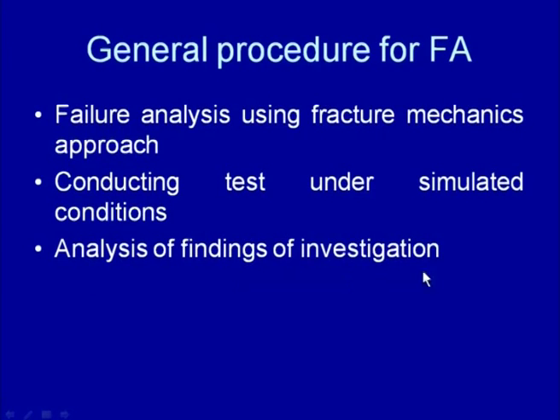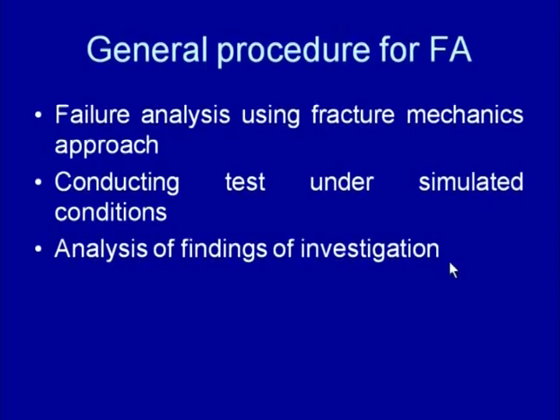Then all these findings are analyzed to see what could have led to the failure of the component, so that the conclusion regarding the failure analysis can be made to identify the main causes that could have led to the failure of the component. So, after the analysis of the various evidences and the findings of the investigation, we try to establish the sequence of events that had led to the failure of the component, and this will help us in establishing whether there was a deficiency in the design of the component, or in the materials, or in the manufacturing processes, assembly, or the maintenance plan. So, what had led to the failure of the component, that particular aspect is identified. Basically through this we try to identify some main factors that have contributed towards the failure of the component apart from the other factors.